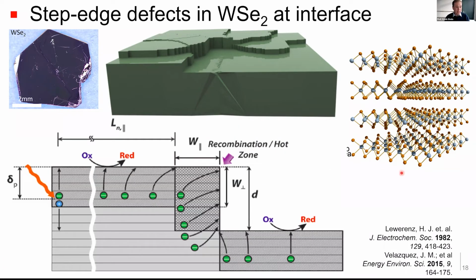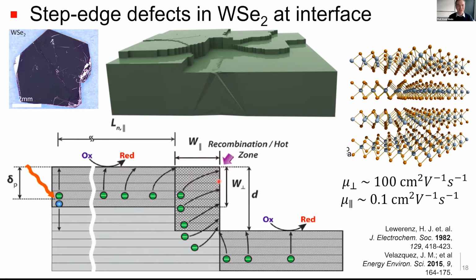In fact, the charge transport in this direction, parallel with the atomic layers, is about 1,000 times faster than perpendicular out of the flake. So what that means is that a charge carrier generated some depth into a multi-flake film will much more quickly move towards the edge, where these edge sites are atomic recombination zones. These charge carriers zoom quickly to kill themselves here at the edge, where what we want is them to move straight out of the surface.